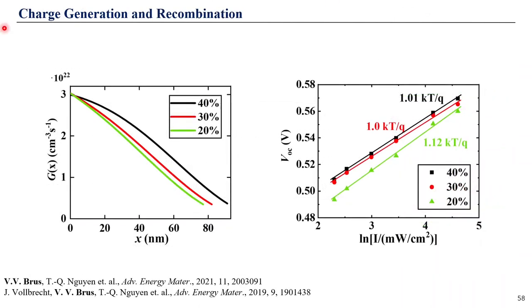So first, we carried out transfer matrix optical simulation, which takes into account all optical constants and thicknesses of functional layers. Indeed, the generation rate drops as we dilute the donor concentration. However, this drop in generation rate can explain only up to 30% of the short circuit current drop. So there is definitely something else going on in the system which has to be understood.